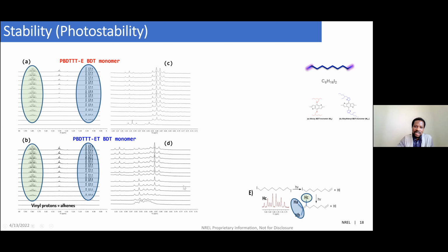Now, when you move to the aliphatic region, we also see appearance of new peaks around 0.89, which is observed to be the formation of an alkyl chain. So in that sense, it means that DIO undergoes homolytic cleavage of the C-I bond, giving you hydrogen iodide, which is a strong acid, and then the rest is an alkyl chain. And this is what we see in this region particularly. That means that DIO under illumination becomes a photoacid.